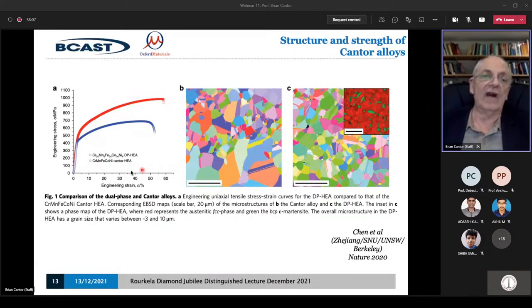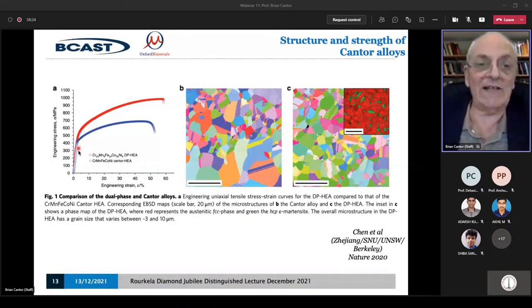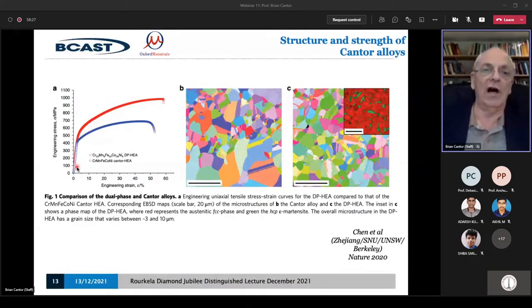So the holy grail has always been, how do you get high strength as well as high formability? If you take a highly formable metal and strengthen it, the formability always goes down, and you end up with a material like ceramics that's got no formability and no fracture resistance, but has now a high strength. Well, it turns out the Cantor alloy has the best combination of strength and ductility that's ever been found.